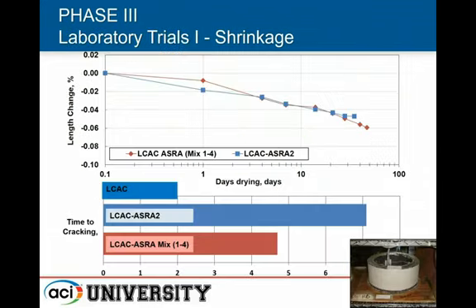So we started to move towards a different type of testing. What we wanted essentially for these patching systems was concrete mixtures that didn't crack. And we began to employ a new test method that has been around for about 15 years or so now, but some of you may not be aware that it's out there. It's a test called the restrained shrinkage ring test.